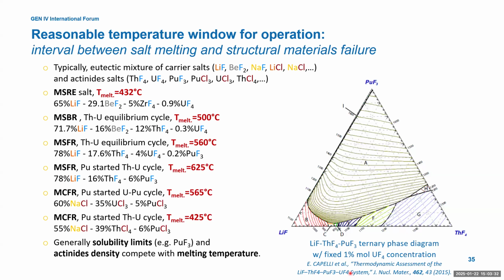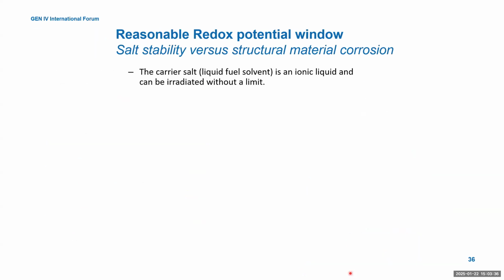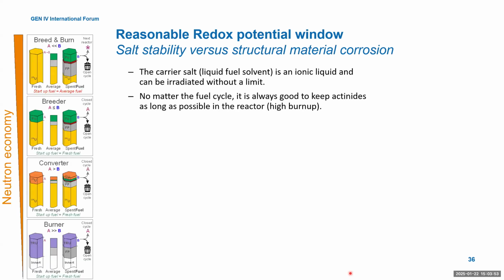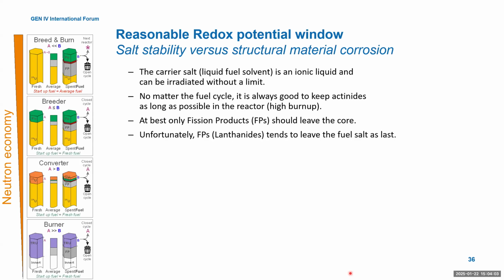features and so on. Similarly, like with temperature window, there is a redox potential window, and there is also a kind of trade-off of salt stability and structural materials corrosion. So the salt itself is an ionic liquid and can be irradiated for infinite time. And no matter the fuel cycle type, it is always good to keep the actinides as long as possible in the reactor. So what you want to remove is actually the fission products, but they don't want to be removed. They are typically the last ones to leave.